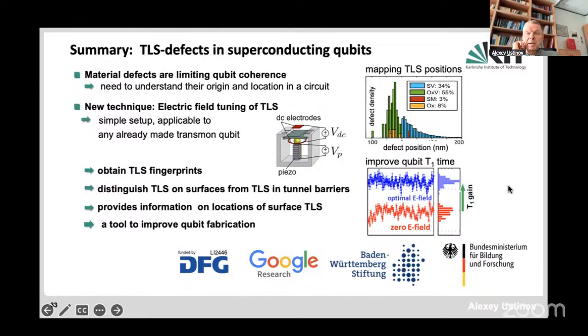There is one type of devices which I believe has a potential to show longer coherence times, the so-called fluxonium qubits. These are flux qubits with very large inductors, which have very low transition frequency between the ground state and excited state. The particular property which one would require to reduce the influence of defects is to reduce the electric fields in the environment. But even transmons made in three-dimensional geometry, which show very diluted field in the environment, have coherence not exceeding, let's say, a millisecond. With fluxonium devices, people have succeeded already to go a bit higher because a significant part of energy is contained in inductive energy, not in the capacitive energy. And therefore, these devices are a bit more robust and also show much larger nonlinearity, which is an advantage.